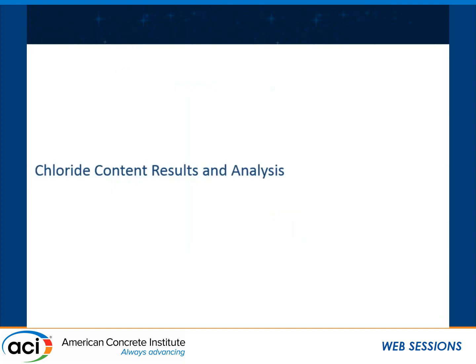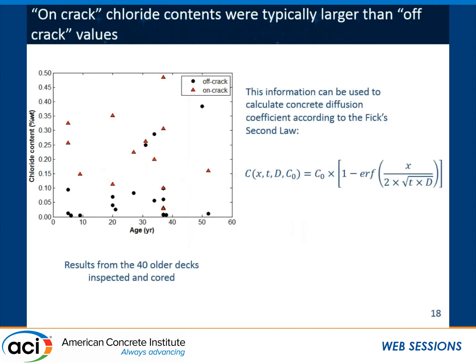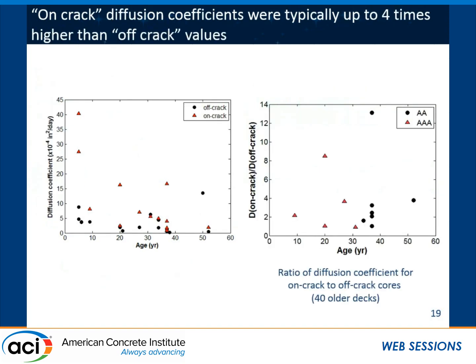Okay, now let's move on quickly to the chloride data. This is raw data on the chloride content from the 40 older decks. Obviously, for the new decks, the chloride contents were none or very small. Here we have, as a function of age, the chloride content, and we can see both the on-crack and off-crack data points. We use this data to determine the effective diffusion coefficient of chlorides into the concrete, which is this graph. And we have the data, again, both off and on crack, so we can, for example, see at the same age, most likely the same bridge, over here, 2 off crack and 1 on crack, and so on.